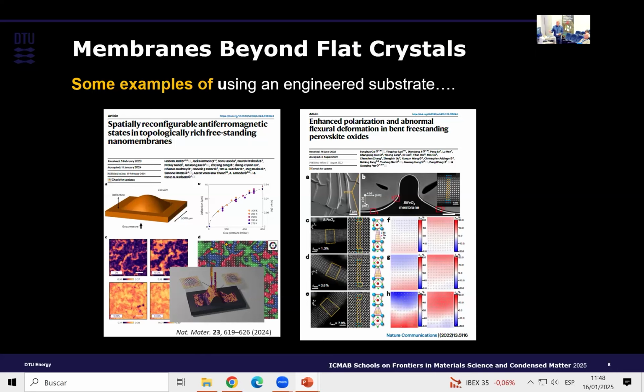In another work, the authors took a membrane and then they just bend it. And they bend it so much that, I think it was bismuth ferrite or strontium titanate, they used both of them. And when they bend it, they could get enhanced polarization due to the bending of the material. So you can bend the material, you can apply pressure. Basically, these are some of the things that I showed before. You can tune it in different ways, and you can induce strain in different ways.